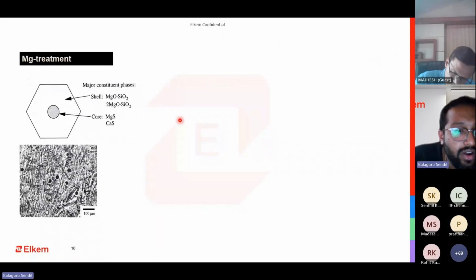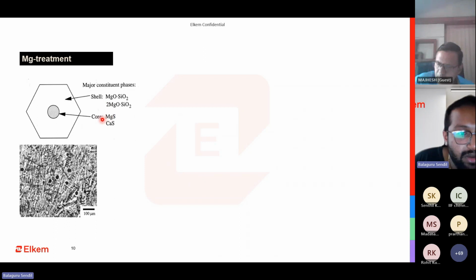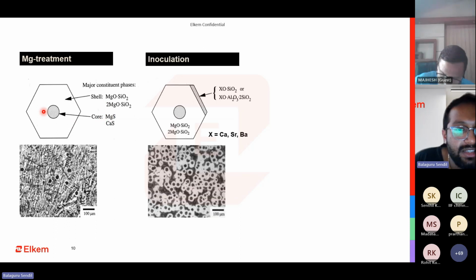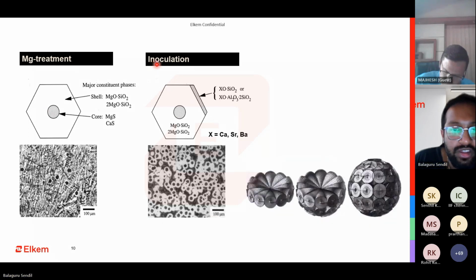So again, this is the microstructure we saw in the first slide. When we are doing magnesium treatment, we are creating enough of these nucleating sites. We are creating magnesium sulfide and calcium sulfides with an oxide shell. The core is always magnesium sulfide and calcium sulfide. Some sulfides we have majority magnesium sulfides and it has an oxide shell. What happens is that after you are doing inoculation, this particular area replicates, there is a lot of vacant sites here. If you look at it in more depth, this site vacancy mimics that of the carbon and the carbon can come and start depositing here. And since it has this magnesium sulfide core and then we have this silicate oxide, it grows into a nice uniform nodule. This keeps building up in a layer and you get a round nodule.